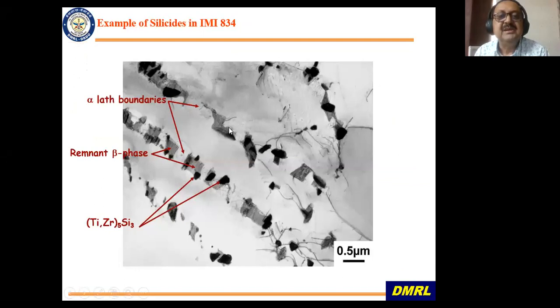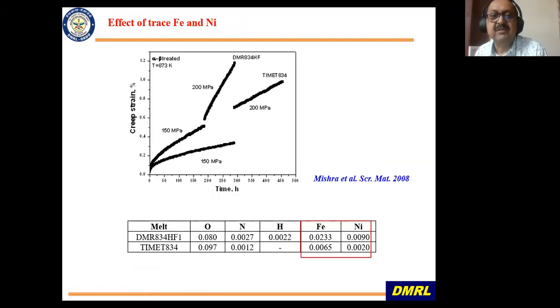Here I am showing you what silicon does. This is an alpha lath. You can see this is a beta lath, supposed to be a beta lath, but it is discontinuous because the amount of beta fraction is less in high temperature near alpha titanium alloys. So what silicon does is it precipitates and blocks the slip transfer, so that deformation cannot pass on from alpha to beta and to another lath. So the slip is restricted, and thereby it improves the creep resistance of high temperature titanium alloys.